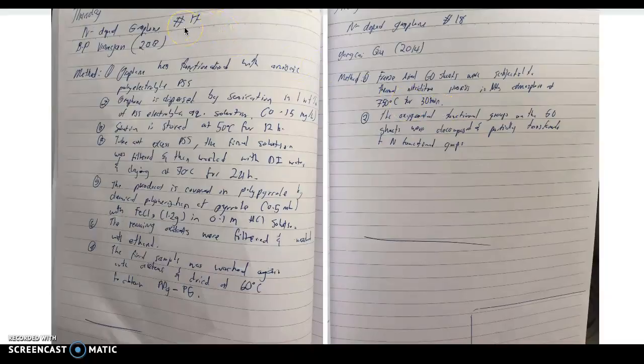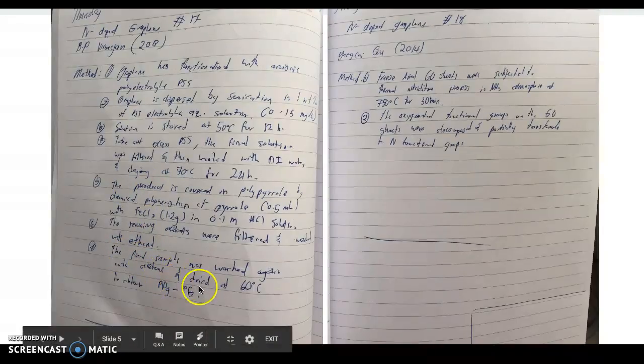Continuing on, method 17 by this 2013 paper by Bingham. This one is pretty dense, but it's interesting that they are using a different material, which is an anionic polyelectrolyte PSS, and the graphene is dispersed by sonication with the PSS electrolyte and stored at 50 degrees for 12 hours. The PSS is then removed and filtered for another 24 hours at 70 degrees Celsius, which is kind of high temperature. But ultimately, you want the sample to be washed in acetone and dried at 60 degrees.